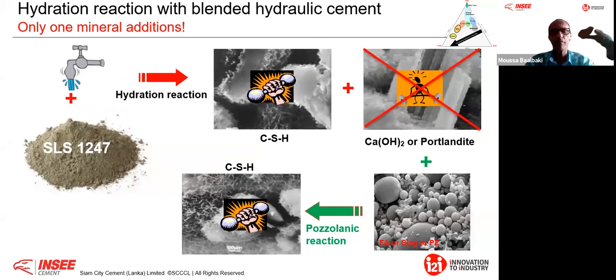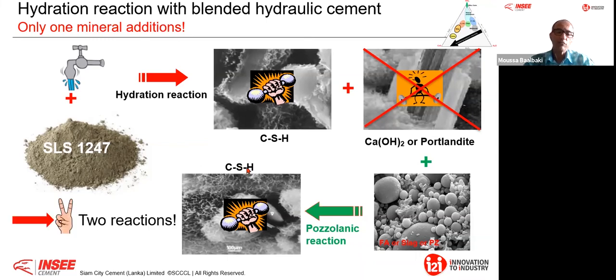That is the main reason. Therefore, it's not about megapascal. It's about to which extent I can increase the calcium silicate hydrate to have a mature concrete where capillarity pores are not percolated, and I will explain later where you have the minimum of these capillarity pores. Therefore, you need to have a glue, but a good quality glue. Therefore, in this cement, you have two reactions.